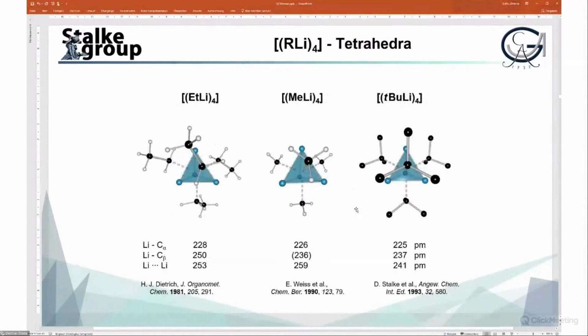The same is valid for the tetrahedra. The first was Dietrich, who determined ethyllithium. As you can see, all the carbons in the beta positions are eclipsed to the tetrahedron. So that is an attractive interaction between the lithium and the carbon.